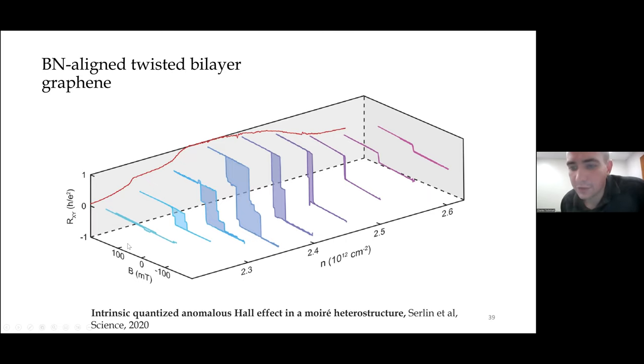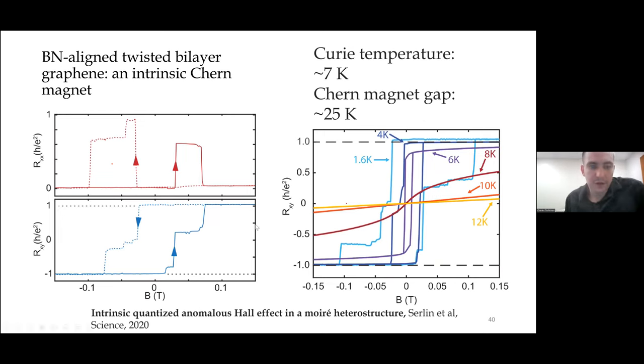So you can take a magnetic hysteresis loop as a function of electron density. So this is sort of zoomed in around that peak that I just showed you. And indeed, you can measure the Hall resistance in that regime. And indeed, we see this magnetic hysteresis loop of the Hall resistance with good quantization for positive and negative magnetic field. So this is one of the magnetic hysteresis loops showing the Hall resistance on the left and the temperature dependence on the right.